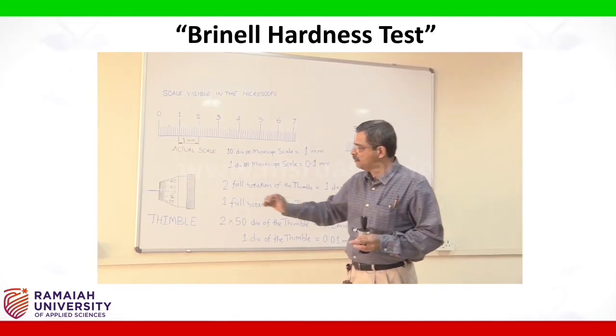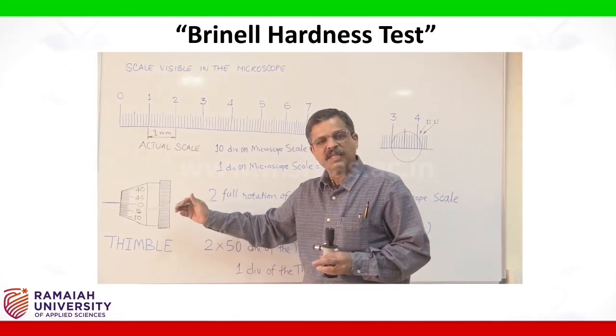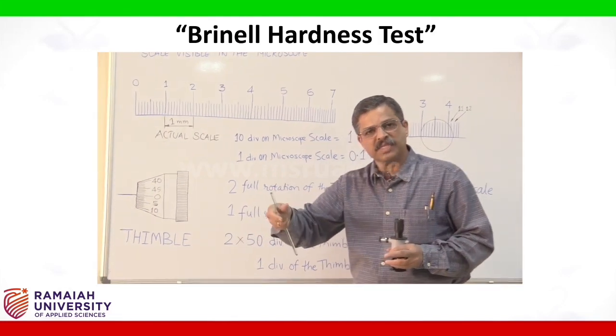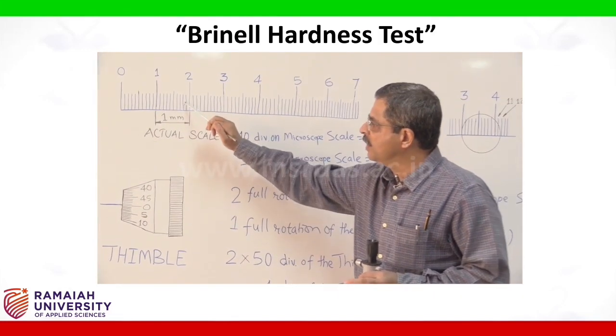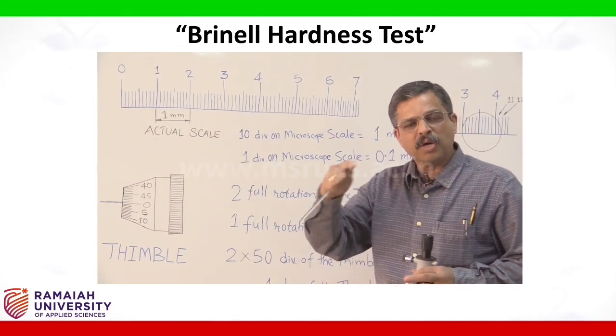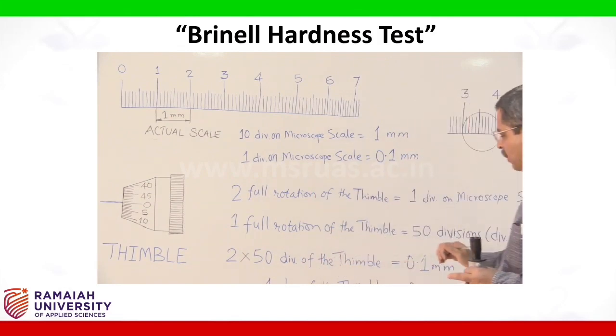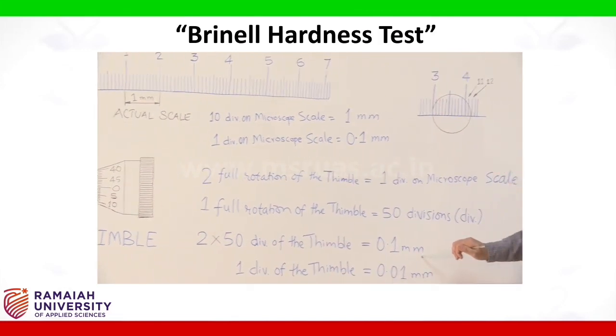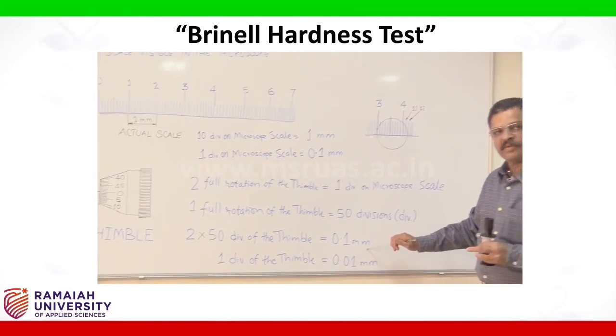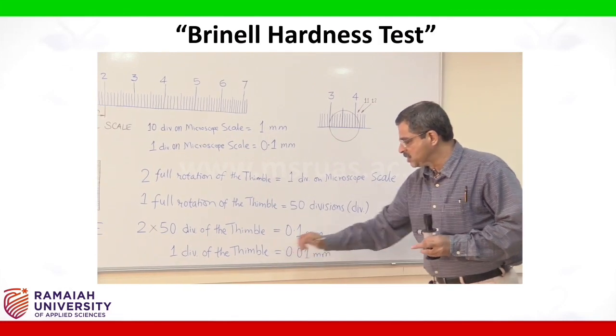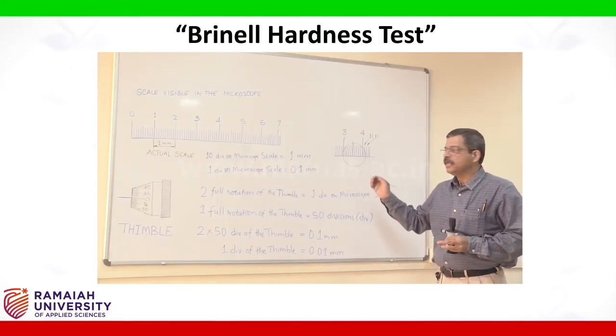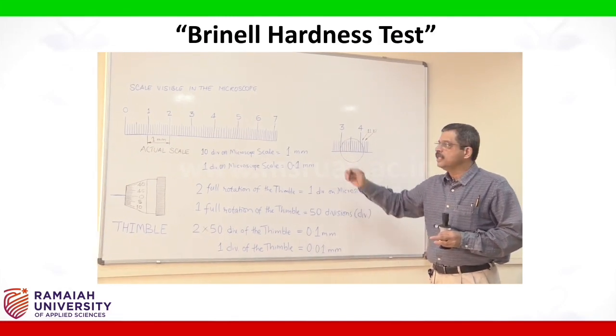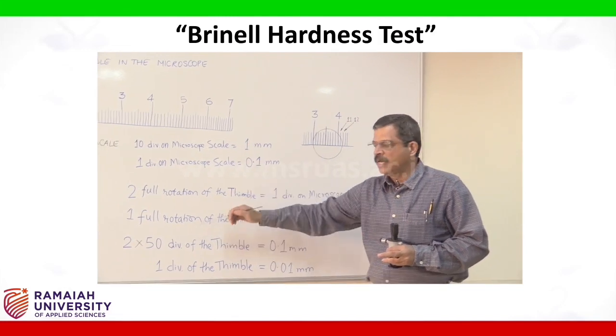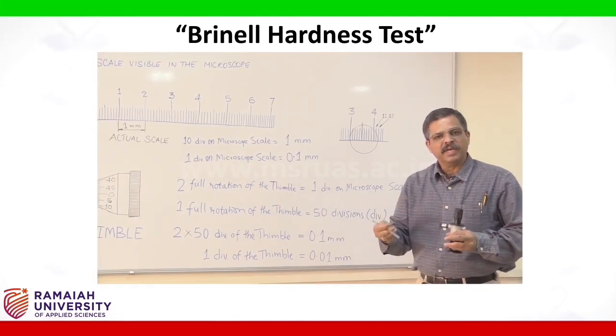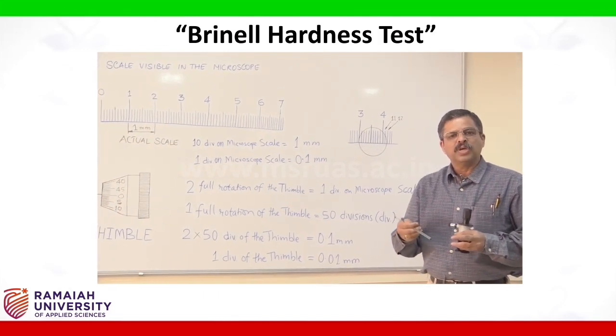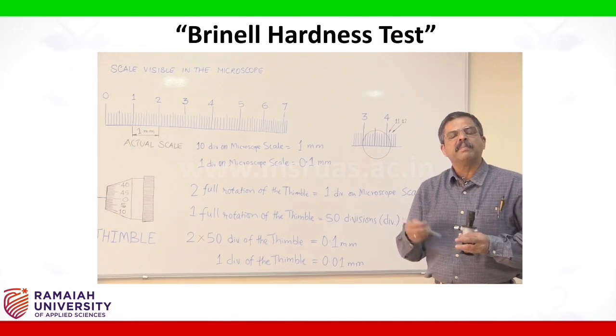One complete rotation of the thimble scale gives us 50 divisions. These 50 divisions, one rotation of the thimble scale, move by 0.05 mm on the microscopic scale. So, 2 complete rotations of the thimble scale move a distance of 0.1 mm on the main scale. Therefore, 1 division of the thimble scale is 0.01 mm. Now, to get the indentation diameter, we have to add the microscope scale value and the thimble scale value. You will get a diameter. That diameter is used to find the Brinell hardness number by applying a particular formula.